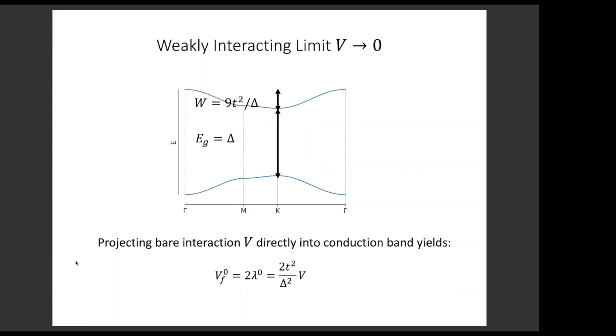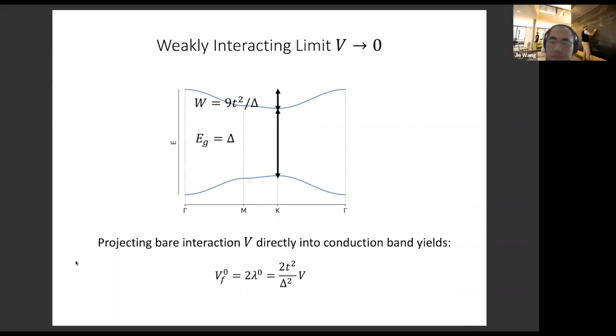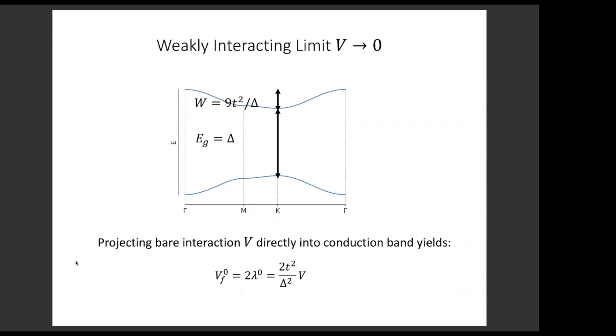It already appears if you directly project the interaction into the narrow band. But interestingly, if you do this direct projection, then the correlated hopping magnitude is 1/2 of the nearest neighbor repulsion. Okay, and we will see that this actually produces no pairing. So if you do direct projection into the narrow bands, although we do get the same type of terms, it is such that there's no attractive pairing interaction.